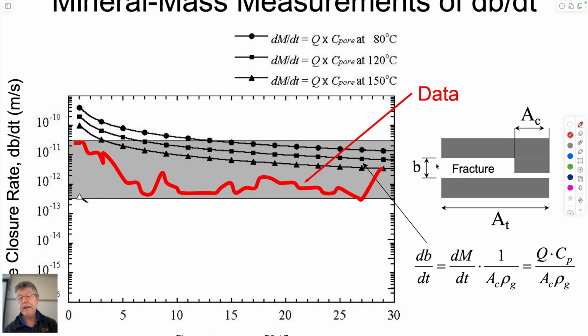Of course, if the fracture permeability is going down with time, it suggests that we're net dissolving material, but for some reason the fracture is growing. So the observational data suggests that if permeability is going down with time, we're net precipitating stuff, and therefore we're occluding the fracture. But that's not what we see. We're net dissolving material and getting this result as a function of that. And so the suggestion is that what we're getting acting in this system is pressure solution.